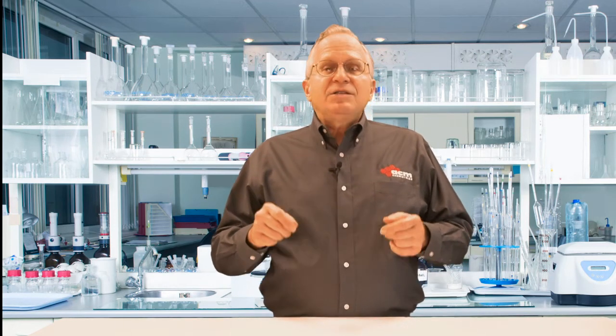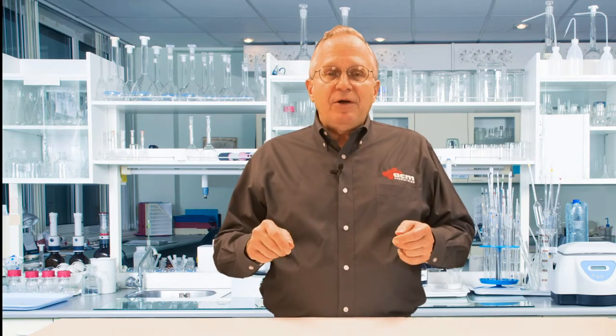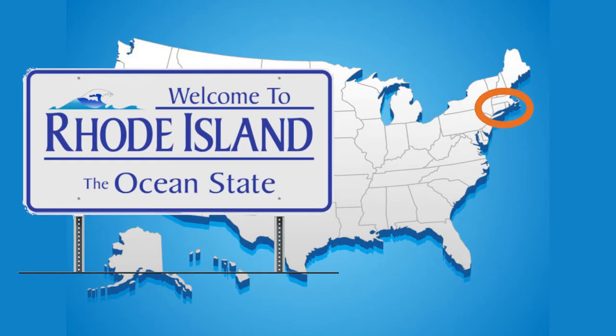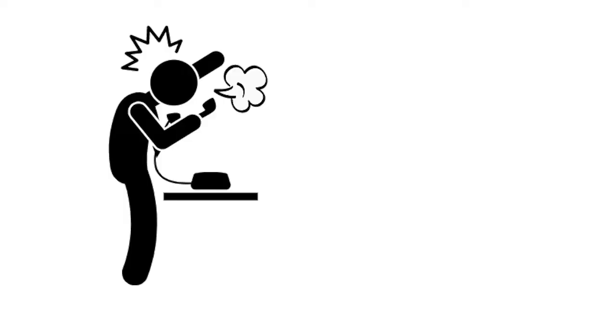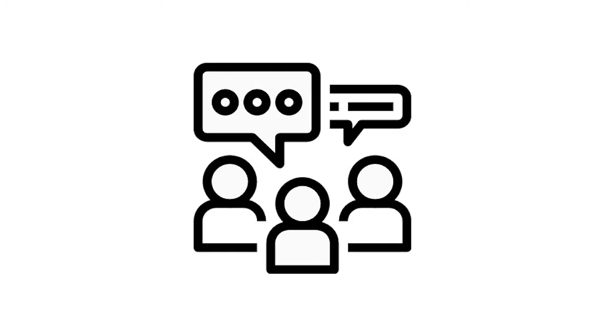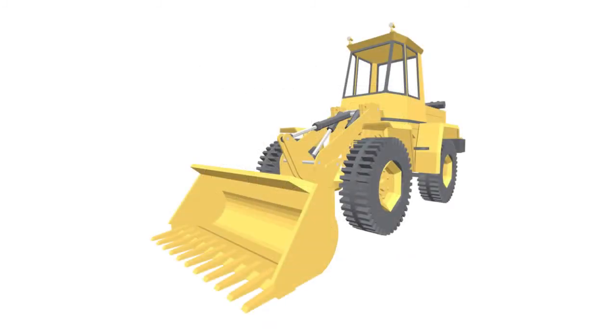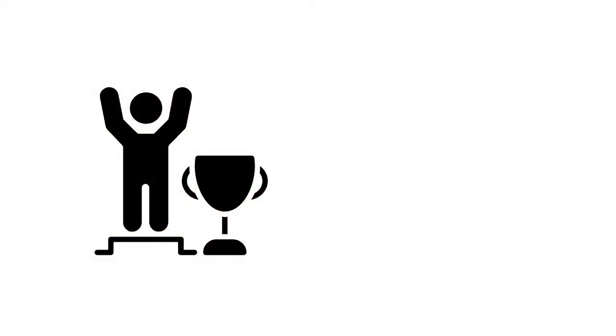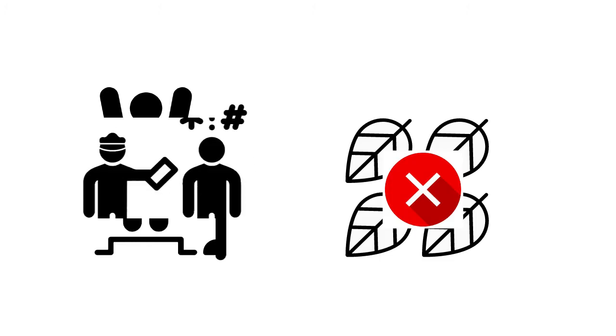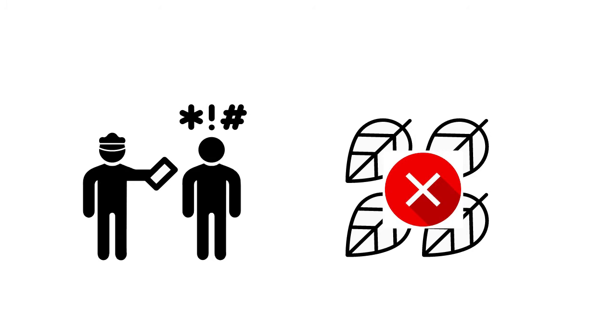But before we jump into raw materials, let's look at our first myth: that only QC folks and machine operators need to know anything at all about concrete or raw material quality. Here's a true story about a block plant in Rhode Island that was having intermittent low-strength issues. Every so often, the chippage and scrap piles would just explode, followed later by customer complaints about cracks and low-quality block. One November, they had a huge customer crisis and called in all the suppliers. One supplier rep noticed the loader operator cleaning the yard, picking leaves and other debris off the ground. Then, with the yard waste still in the bucket, the operator went over to the sand pile, loaded up, and dumped the sand along with the yard waste into the hopper. The loader operator thought he was doing a good job cleaning the yard — he had no idea that the organic material, like the leaves, would severely affect the strength of the concrete block and result in a large claim against the company.